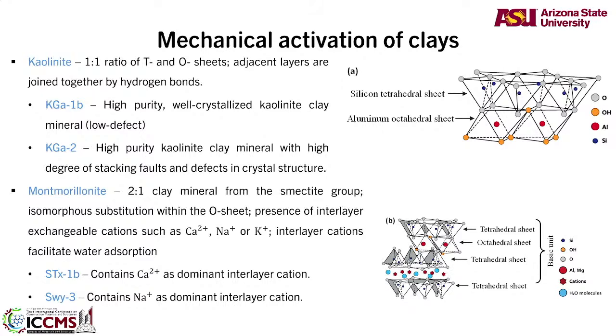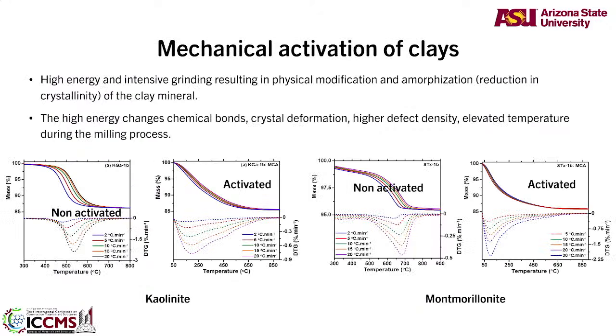Clays are not normally very reactive because they have these tetrahedral sheets of silica and octahedral sheets of alumina that are very happy with each other. They don't want to do anything. So how do we make them react faster? You can really, really grind them, mechanically grind them, break them into much, much finer crystal structure levels and create much more reactivity.